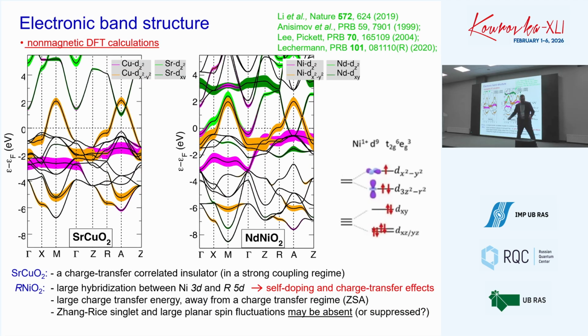What, as theoreticians, can we say about the electronic structure of these materials? This is our starting point: what density functional theory can tell us about this system in comparison to cuprates, to infinite-layer systems. This is just a plain calculation where no correlations are involved. These are metals. You see, like in cuprates, a large hole-like Fermi surface sheet around the M point.